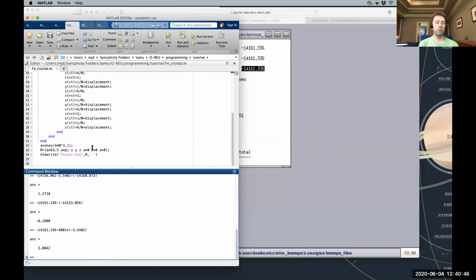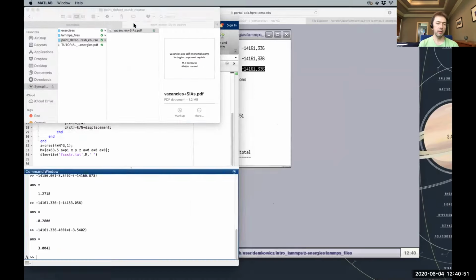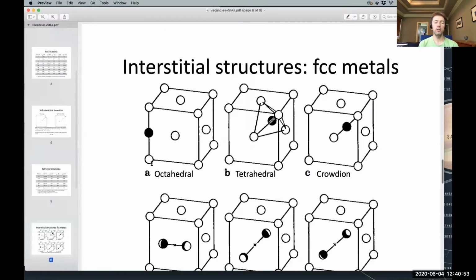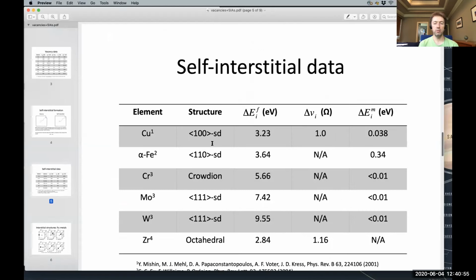3.0042 electron volts. How does that compare to the actual formation energy of a split dumbbell interstitial for copper? Okay, so in copper, the energy of a split dumbbell interstitial is 3.23 electron volts. So we are actually slightly underestimating the formation energy of a 100 split dumbbell in copper. The energy difference is a little bit bigger than what we had before.